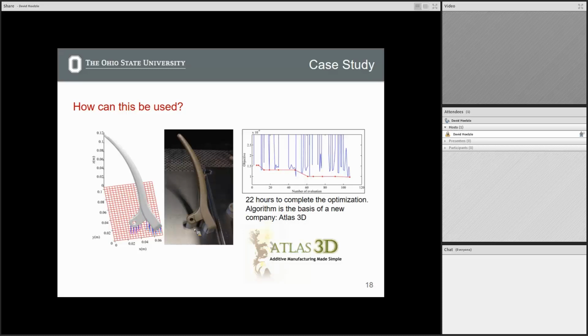So we have to support the part somewhere. If you go down just a little bit lower to get efficient thermal transport, you have to support it the whole length, and then that creates a thermal constraint and it's holding it fixed. So actually it's better to have most of the part entirely free, as long as you don't hit some sort of temperature limits. So in this optimization, we actually had bounds on what the temperature could be, because if you want to get minimal stress, you actually print this completely vertical. And so that is another constraint that we tried to hold down, but that part would get really, really hot. So this is what is determined to be optimal.